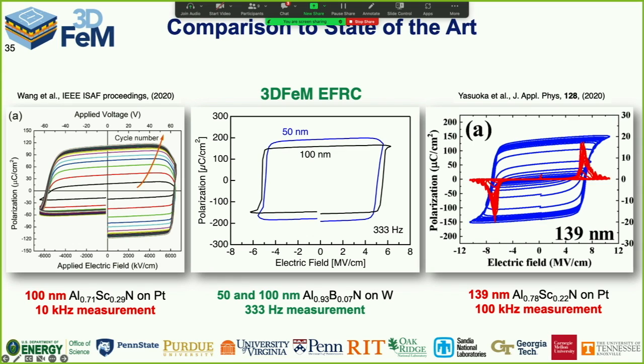So this shows data for an aluminum scandium nitride. This is beautiful work out of the University of Pennsylvania, where they've scaled the thickness. And you see that hysteresis loop looks a little funny. If you look at the top of the hysteresis loop, when I decrease electric field, the apparent polarization goes up. Okay, that's bad physics. Polarizations, excuse me, will tend to align parallel to the electric field, not anti-parallel to the electric field. That is an artifact associated with leakage.